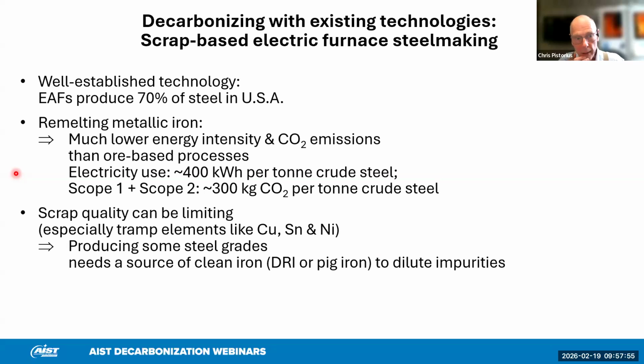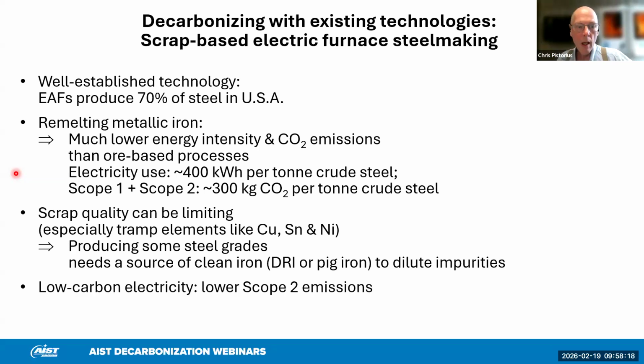Scrap quality is really important, especially tramp elements like copper, tin, and nickel, which build up in the scrap pool as we keep on recycling the steel. For some steel grades, this matters less. Others are very sensitive to copper and tin, especially. So one does need a source of clean iron to dilute the impurities.